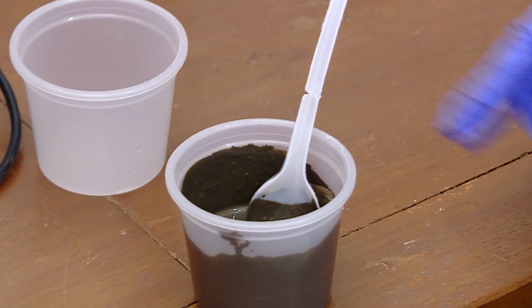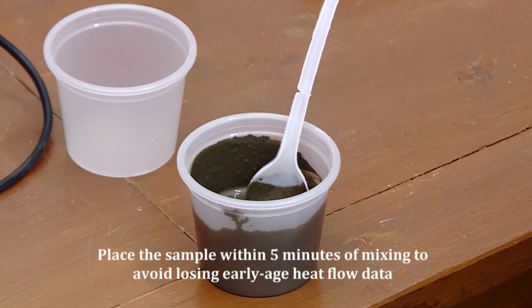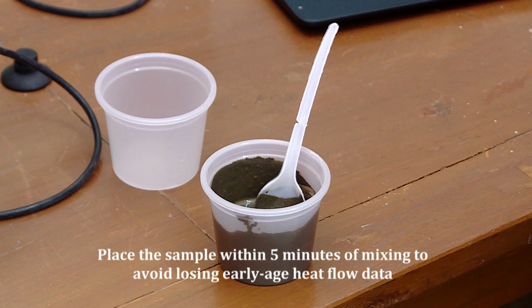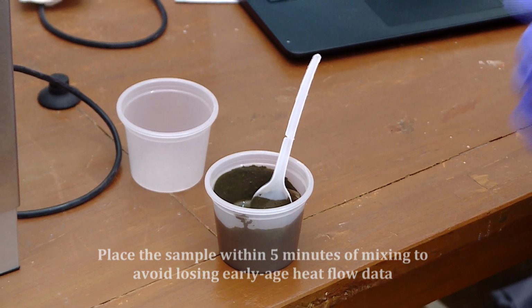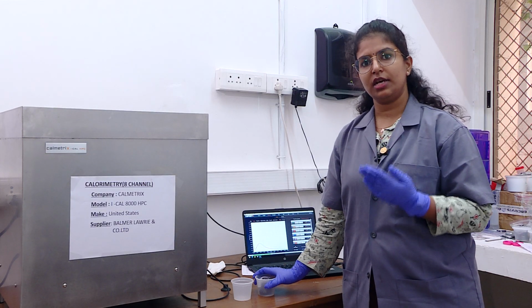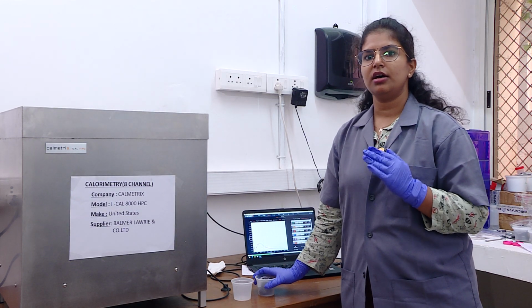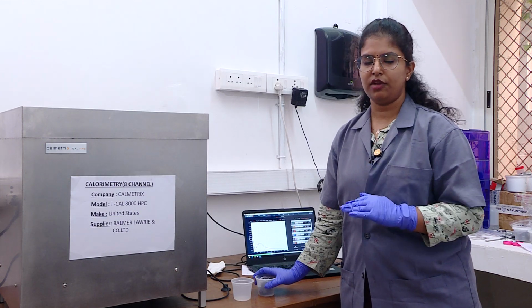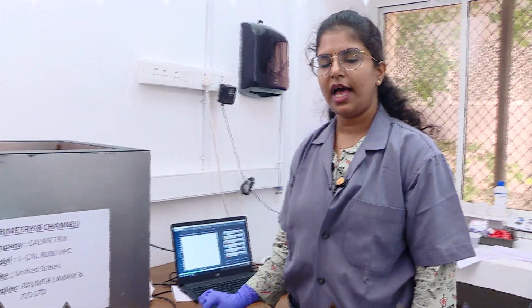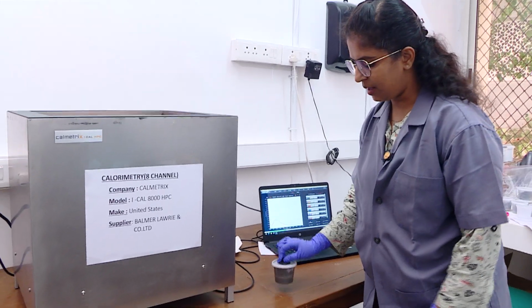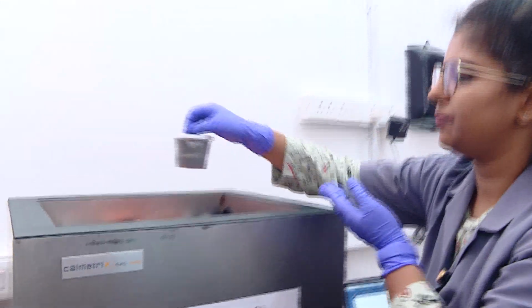Now the mix is steady. After mixing, we have to keep the cement paste within 5 minutes to avoid the loss of early age data. The raw materials for the experiment need to be conditioned at the required temperature for at least 24 hours. After mixing, we will place the sample inside the channel.